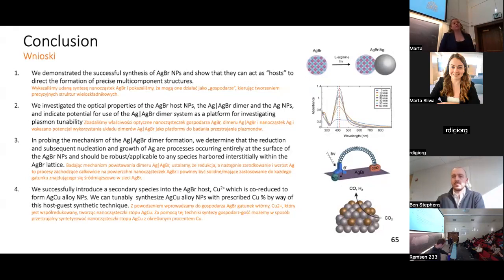I actually think the CTAB is more so forming solution phase micelles around these particles as opposed to actually interacting with our surface. So when we spray or airbrush them onto that carbon substrate, there's probably just loss of ligands. We also perform purification steps and concentration, so there's also removal of ligands there too. That's a great question.